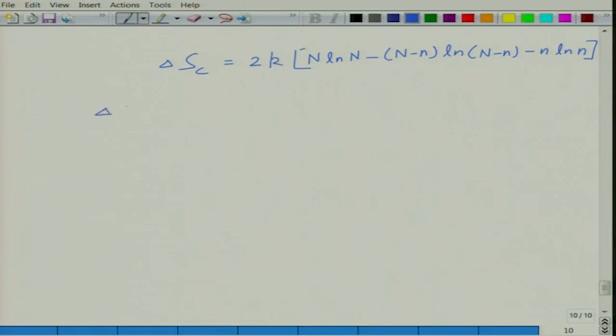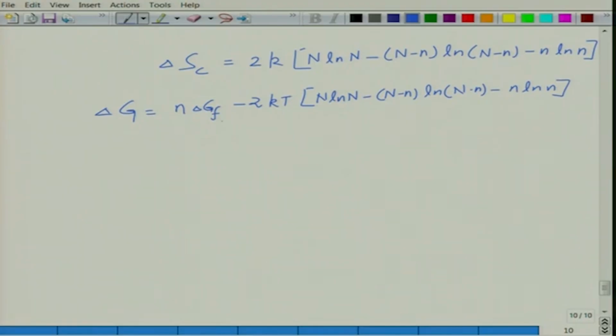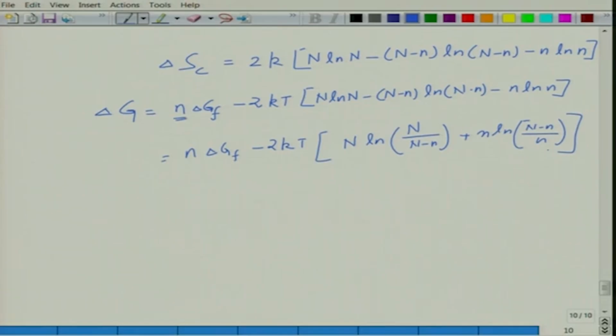and hence the total energy change is delta G equal to n delta Gf minus 2 kT, n ln n minus capital N minus small n ln. And so we can write this as, let us say, we write this as, with some more changes here, n delta Gf minus 2 kT. So just do some more approximations, and you will get something like that. Okay, you will get these expressions.